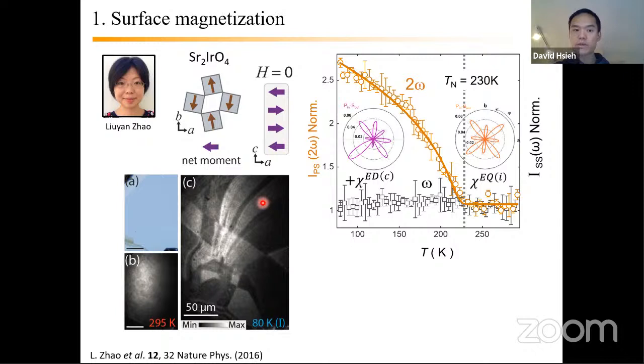And we keep our beam there, let's say, at the point where my laser pointer is, and you perform temperature dependent measurements. At least what we find in this material is that at high temperatures above TNéel, we're dominated by a bulk electric quadrupole response of I type. Okay, and then as we cool down below TNéel, you see this huge uptick in second harmonic, but no change in the linear response, which are these open black squares down here. Okay, and if you look at the RA pattern, it evolves from looking something fourfold, reflective of the underlying crystallographic symmetry, to something that has only C1 symmetry about the C-axis, okay? And that corresponds to your surface magnetization now choosing a direction, okay?